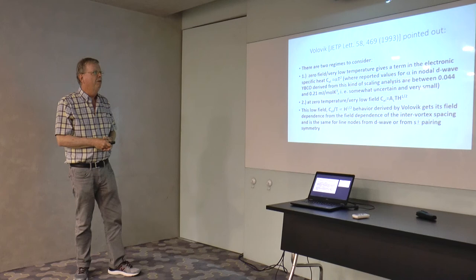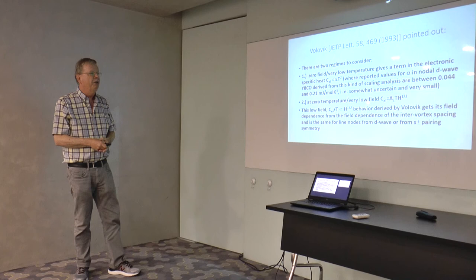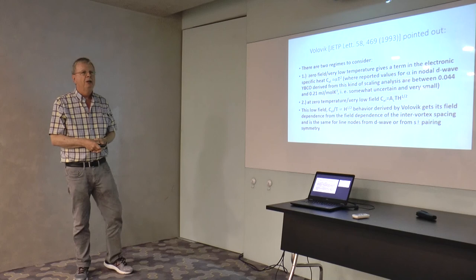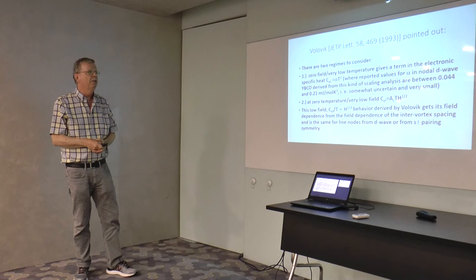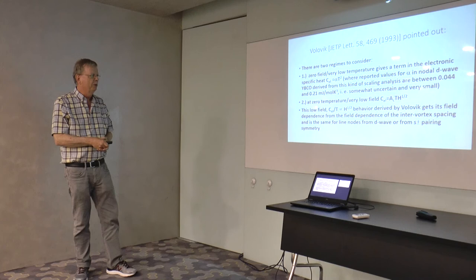And then if you start putting a magnetic field on and you've got some magnetic defects, then you're really dead, because things move around according to how the magnetic defect responds to the field rather than the Volovik Doppler shifting around the node. So if you're in this other limit, very low field and very low temperature, you get this behavior, which is the advertised behavior.